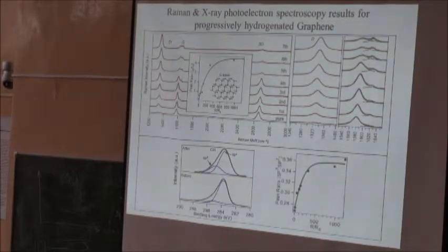Okay, so the same thing we did with X-ray photoemission spectroscopy, XPS. If you look at before functionalization, this peak corresponds to sp2, and this is very small, almost zero, for sp3. But after functionalization, this becomes strong and this becomes weaker. When you plot in a stack, you don't see a very big change, but if you plot this ratio, the sp3 peak becomes stronger and stronger. This is also another evidence for the sp2 to sp3 transition.